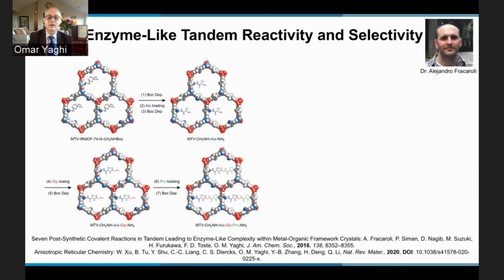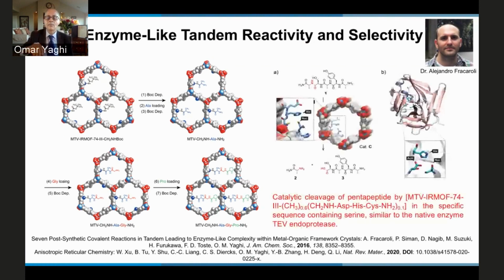You can think of it as a forest of different functionalities, okay? Some you want and some, from a traditional point of view, you don't. You can think of them as impurities, but to us, they are opportunities to decorate the interior of the pores with heterogeneously arranged functionalities. We call them multivariable functionalities. The backbone is ordered and is unchanged, but the interior is full of heterogeneously arranged functionalities. And the power of this heterogeneity is that a substrate floating through the structure could sample nearly an infinite number of environments. And therefore, one can affect very selective reactions.